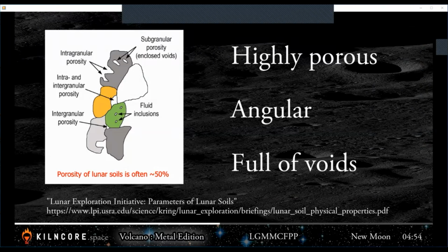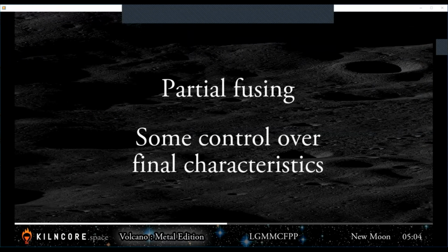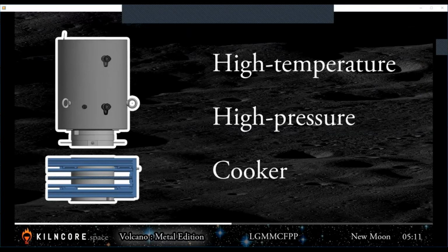Loose regolith is therefore full of voids, but not by itself able to support slag being pushed through it without being destroyed. To transform it into a usable ceramic filter requires at least partially fusing it and having some control over the final characteristics. Using an appropriate hexagonal mold and a variant of the high-temperature, high-pressure cooker, such as our